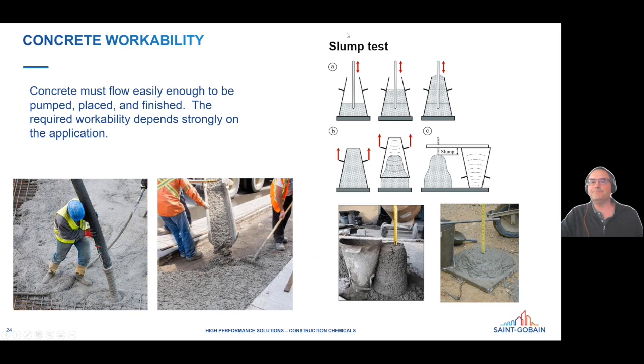And on the right here, we're seeing a slump test. You just fill up this cone with the concrete, remove the cone and let it settle down into its final configuration. And the slump is just the distance that it slumps downwards in the vertical direction. And you can also measure the spread flow, which is how much wider the base gets, so sort of equivalent. Okay, so now we've set the stage to talk about concrete water reducers.